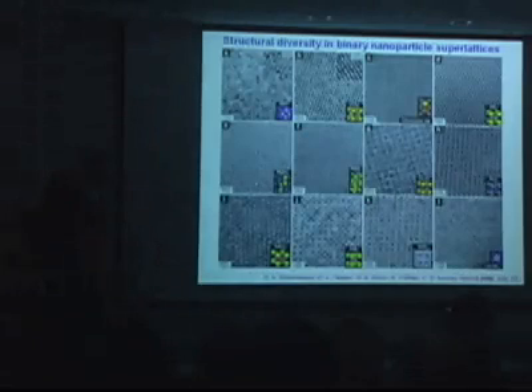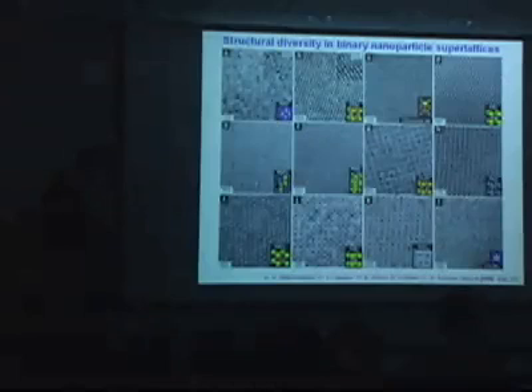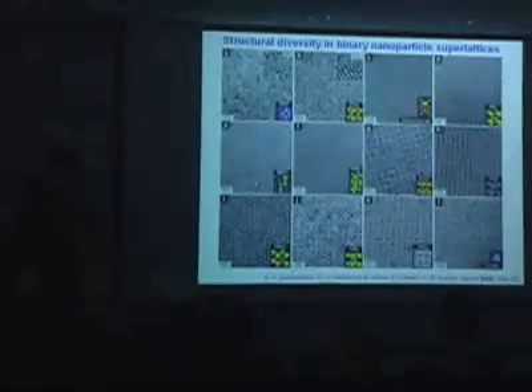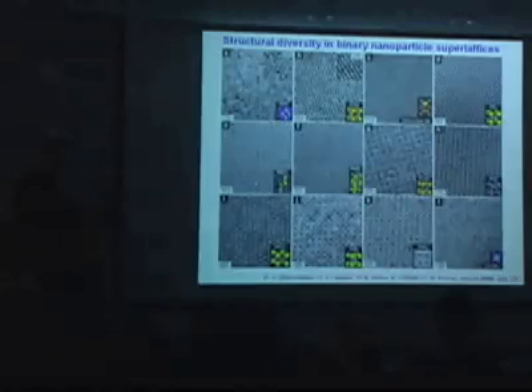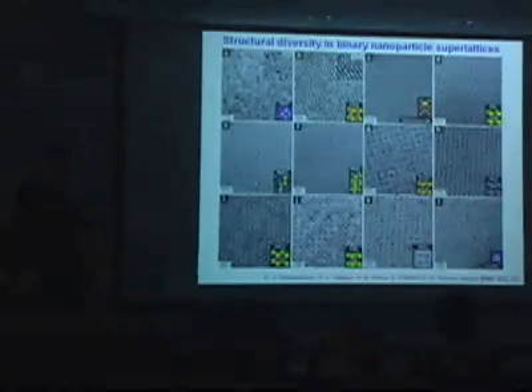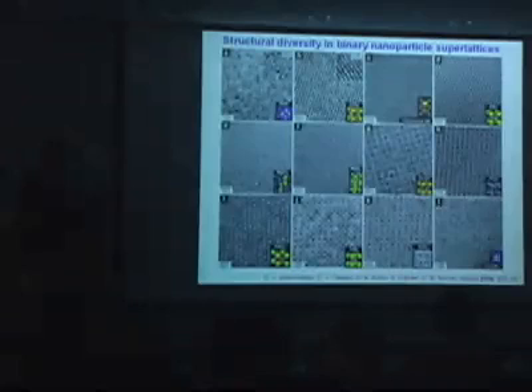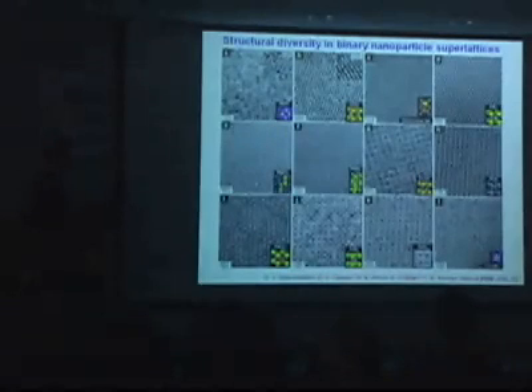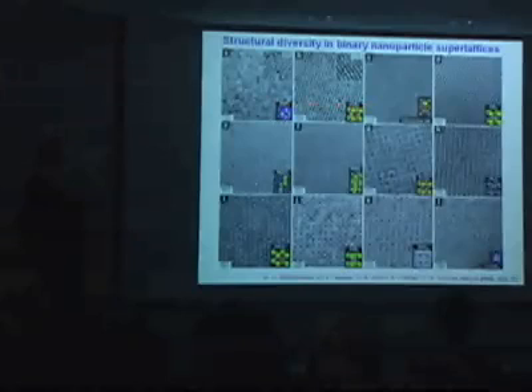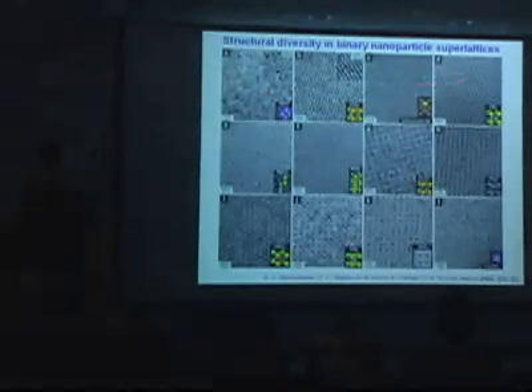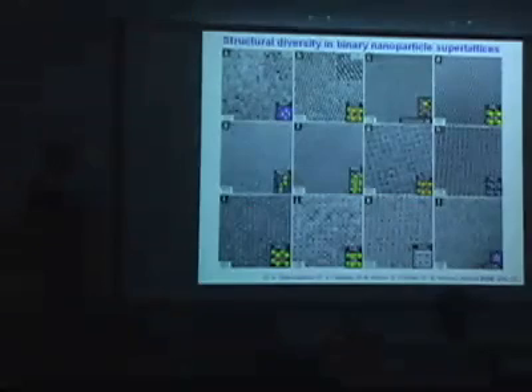Our contribution to the field was that some years ago we found enormous structural diversity in what can spontaneously self-assemble out of a fully disordered solution containing only a mixture of two types of spherical particles. And as you can see, we can have many different unit cell types. For example, this picture shows 12 different